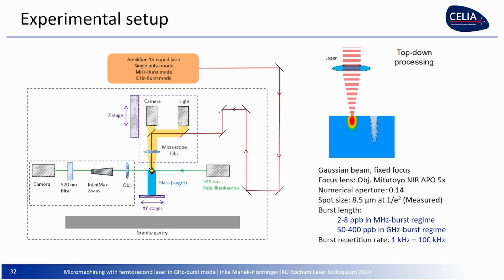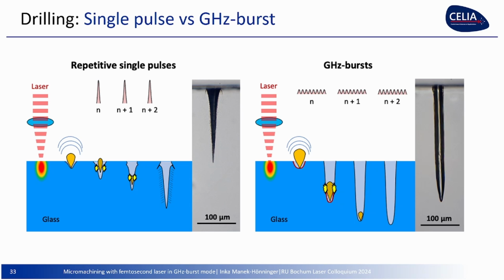So, first observation: you have repetitive single pulses and you have GHz-bursts. The holes don't look the same. They have a different morphology. In repetitive single pulses, you have a strong conical form, and you have some cracks here at the entrance, but all along the hole, you still have them. With GHz-burst, you have a very, very smooth and almost cylindrical hole. So the morphology is not the same. That was a big study. Let me show you what we saw.